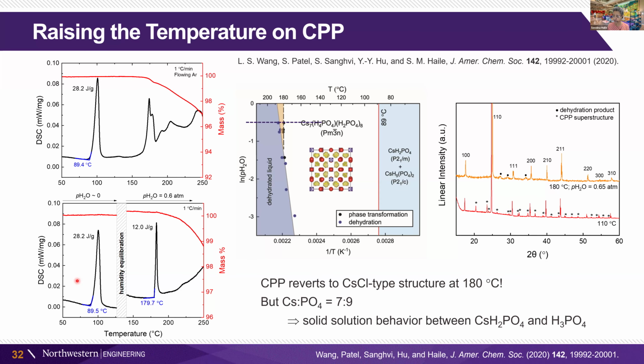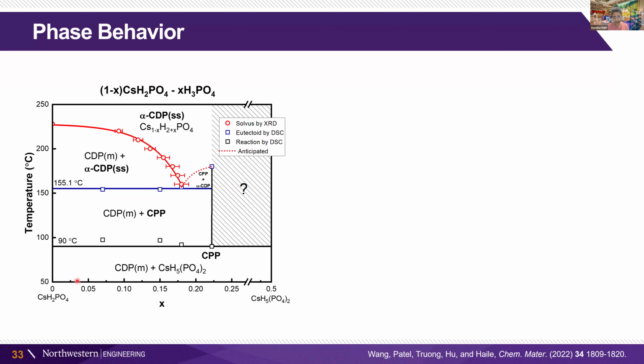now all of those superstructure peaks are lost, and we have a pattern that looks exactly the same as cesium dihydrogen phosphate, which tells us now remarkably that there is solid solution behavior between cesium dihydrogen phosphate and effectively phosphoric acid. And we put together the phase diagram, and we see that there is a wide range of the region which has this behavior. So I've shown you the X-ray diffraction data for the CPP and the DSC results for